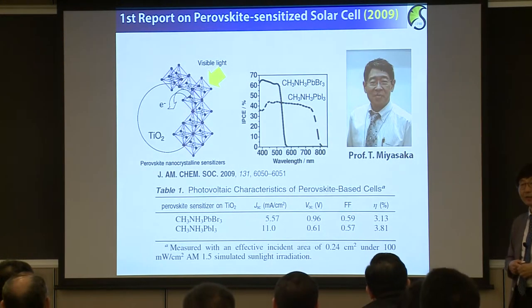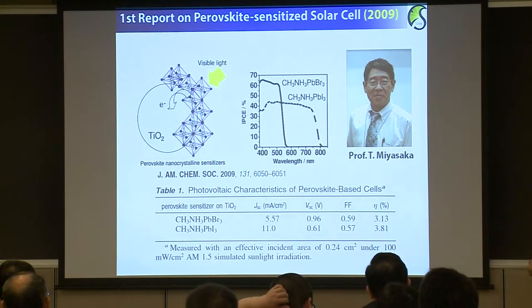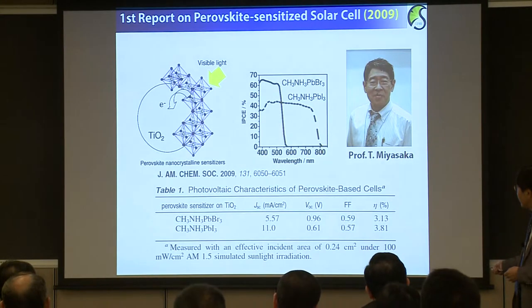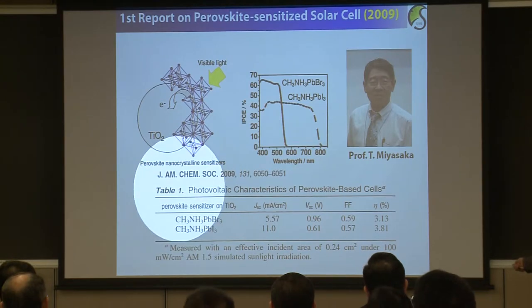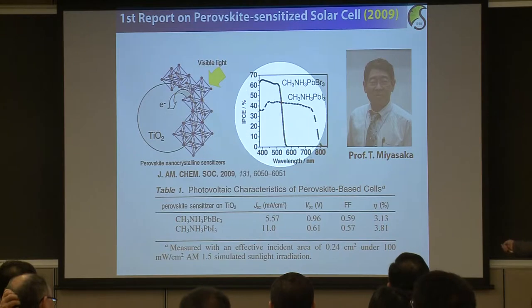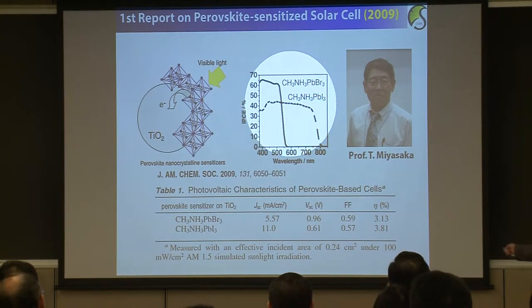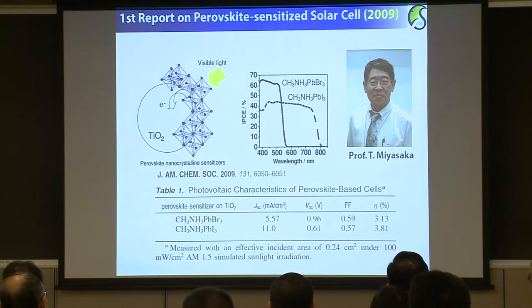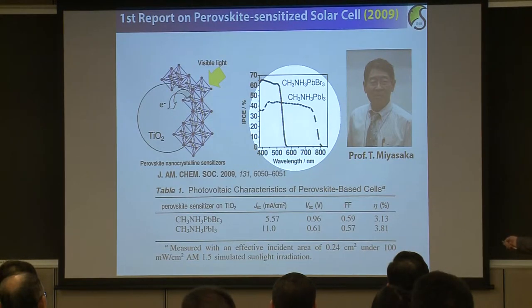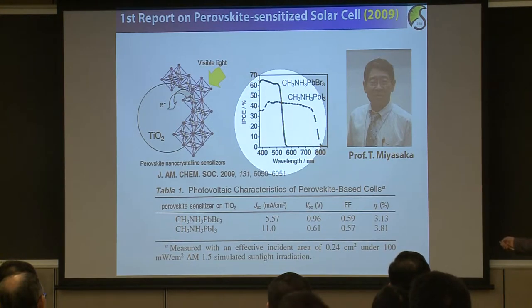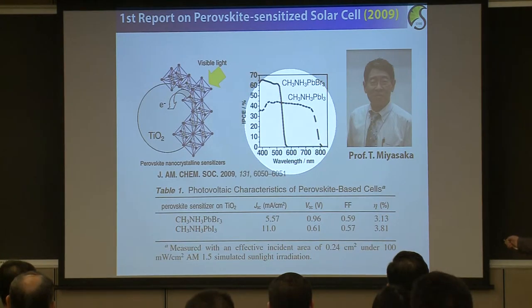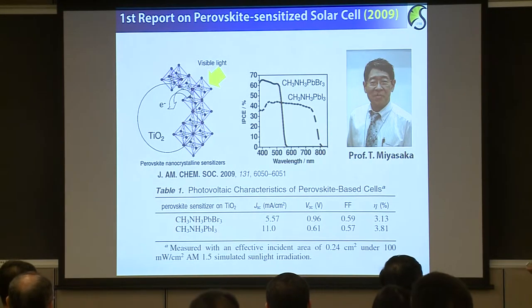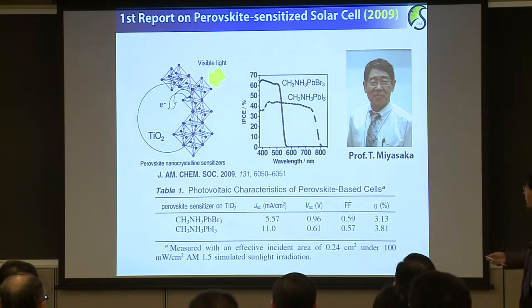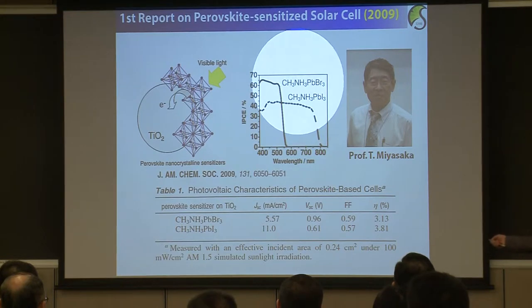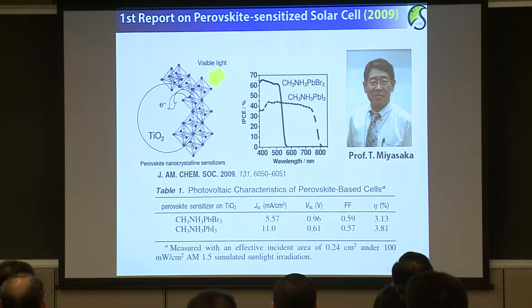And then, while we were forgetting about the perovskite solar cell, Tom Miyasaka eventually published a slightly increased efficiency, about 3.8%, using iodide perovskite in the JACS communication. So this IPCE spectrum is the same as he talked about in the 2007 conference. And then this is very important. You see, the methyl ammonium lead iodide, the maximum IPCE is less than 50%, okay? Very low efficiency. But the shape of the IPCE is pretty excellent because they can convert photon to electron in the entire wavelength region. So if you improve it further, for instance up to 80% or 90%, then you can have very high performance.